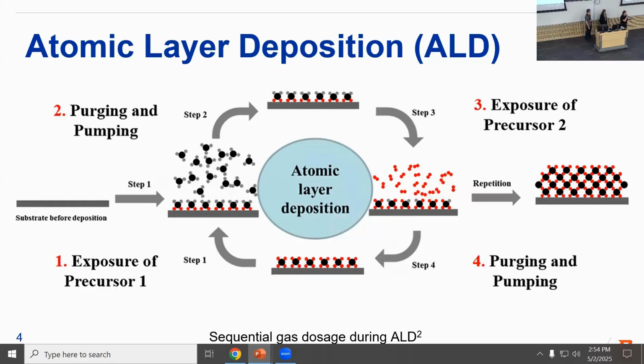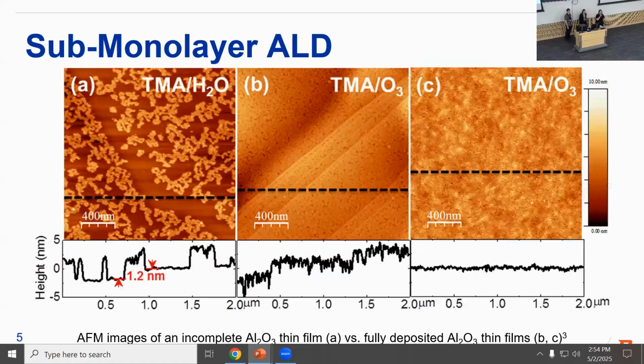Once this monolayer has been formed, it is purged and pumped from the main chamber, and precursor 2 is introduced into the chamber. This precursor is then allowed to react with the monolayer formed in the previous step, and then this is also purged and pumped from the chamber. And this cycle continues until a target thin film thickness has been achieved.